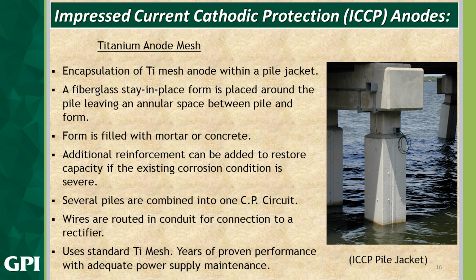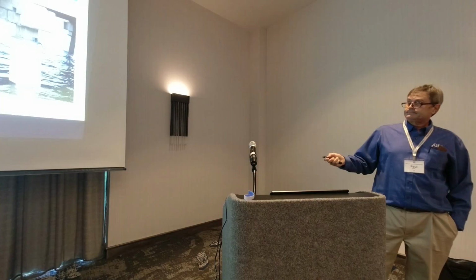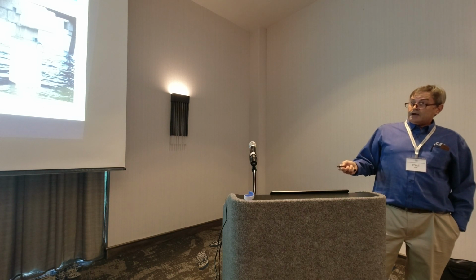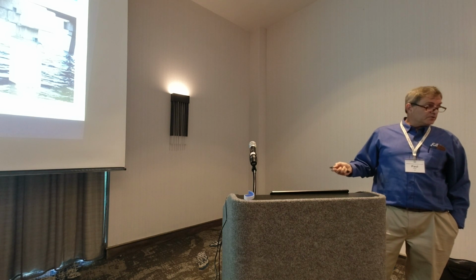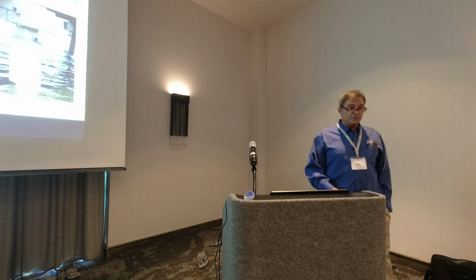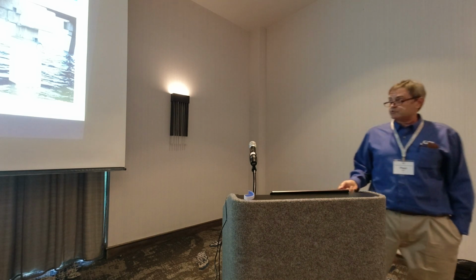So we've got the encapsulation of the titanium mesh anode. That's inside the jacket. We just saw a picture of that titanium mesh. Well, that mesh has been placed inside this jacket around the existing pile. It's a stay-in-place form. There's an annular space between the mesh and the existing concrete, and you can see where it's been filled here at the top. Additional reinforcement can be added if you need to get back to your original structural capacity, or you want to increase structural capacity.